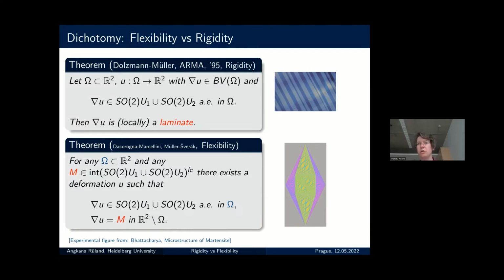So only structures of this type, and this indeed is an experimental picture from such materials from Bhattacharya's book, only these type of simple laminate structures arise. So only solutions which are constant in one direction, depend on the corresponding orthogonal direction, and which are rather rigid in that only this direction or the orthogonal direction is present. Okay, but while this condition seems quite mild, physically reasonable, if you drop this condition, something very, very different happens. The situation changes quite dramatically.